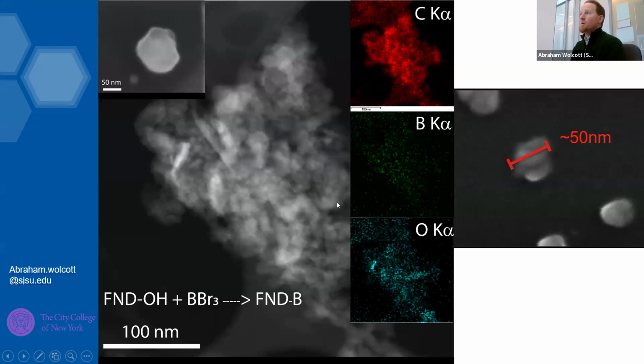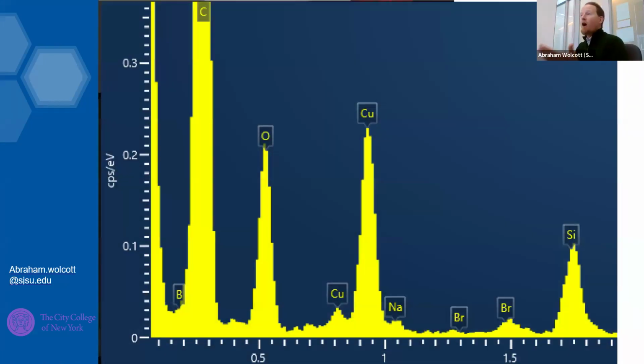We can use energy dispersive X-ray spectroscopy to confirm that we've got carbon, maybe a little bit of boron, but you shouldn't really trust me on that, and then quite a bit of oxygen that's remaining on the surface. The problem with EDS, folks, is that big carbon signal is right by the boron. And so Virginia Altoe at the Molecular Foundry would say, no way, we're not going to use EDS to confirm that boron is on the surface because it's too embedded on this leading edge of the carbon. So then we have to use surface sensitive techniques like XPS, like X-ray absorption spectroscopy to confirm what's going on.